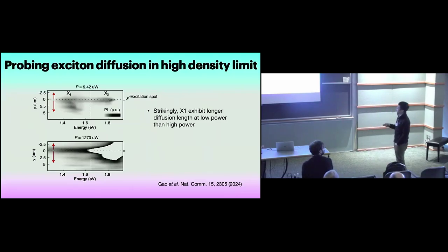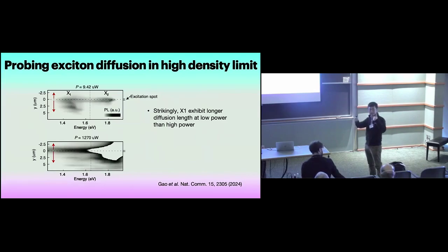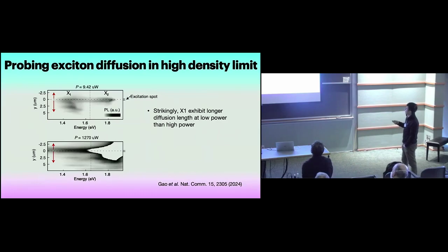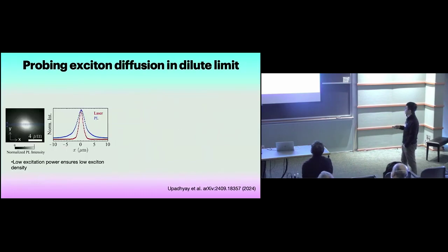We attribute this to the formation of correlated states, exciton Mott states, because we assume that's when you reach 1 exciton per moiré unit cell. That's when the diffusion of excitons gets suppressed. Okay. So this is the diffusion in the high density regime where we create a lot of excitons. It turns out that we can also look at the dilute limit, right? So we can create a small number of excitons and look at how the electron filling influences the diffusion of the excitons. So this is one example where we use a very small laser power, around 1 nanowatt per micrometer, and look at the diffusion of the exciton.